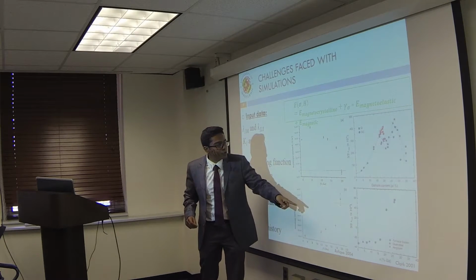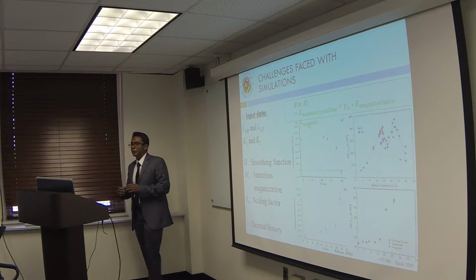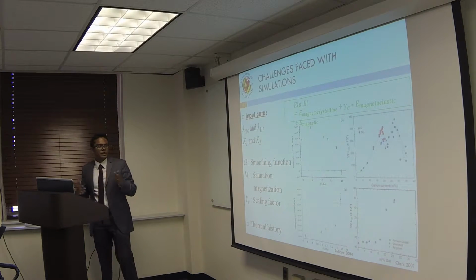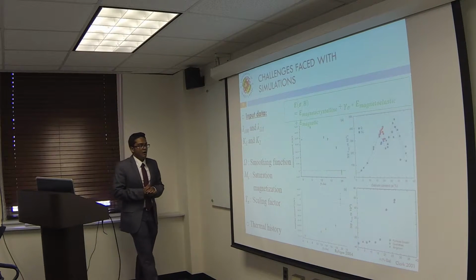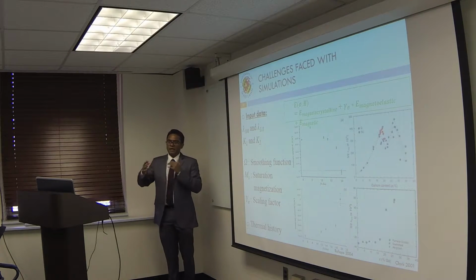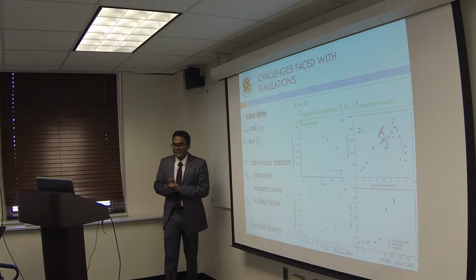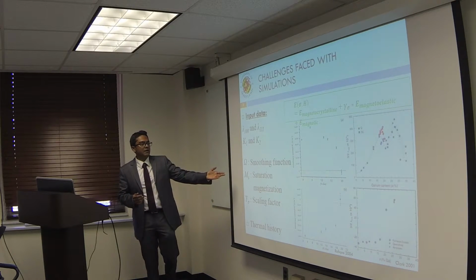The values of K1 and K2 are shown in these 2 plots, and as you can tell, again, it's pretty sparsely populated, and I had to interpolate and extrapolate past 20% to be able to get the simulation to work. We had to introduce a smoothing function as well, which means we had to play with the values to make sure that it fits the experimental results. And then finally, magnetic saturation had to be determined experimentally.